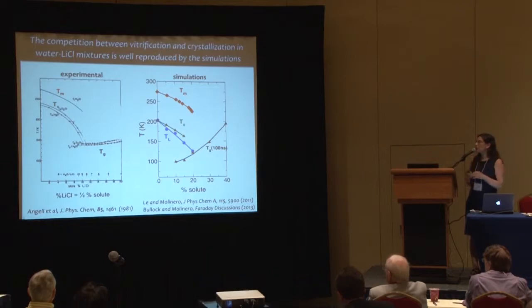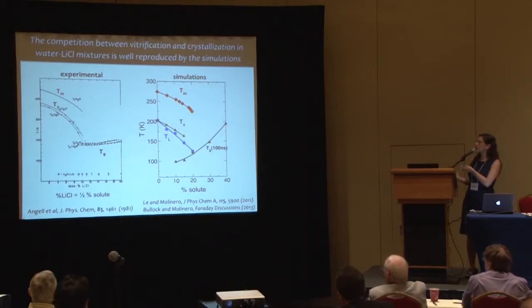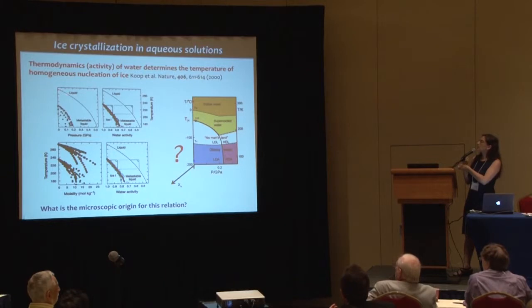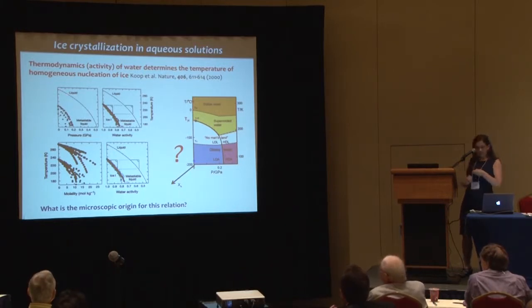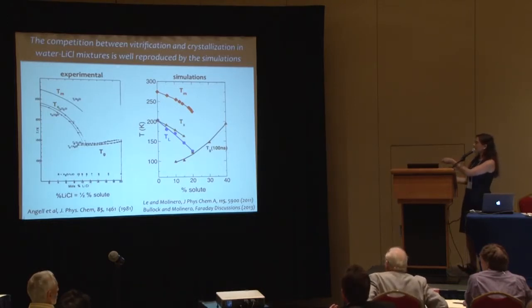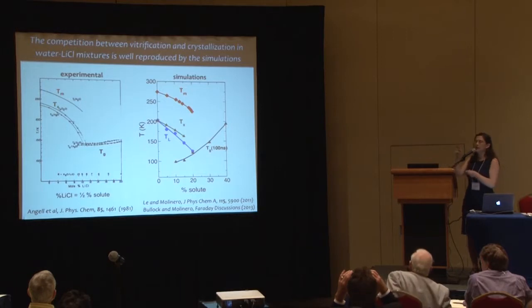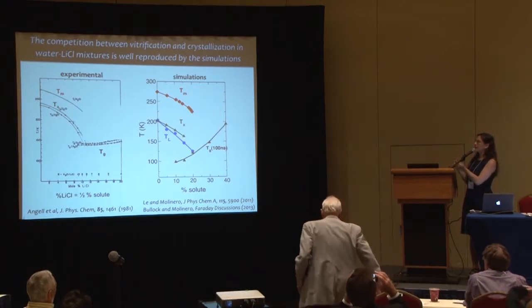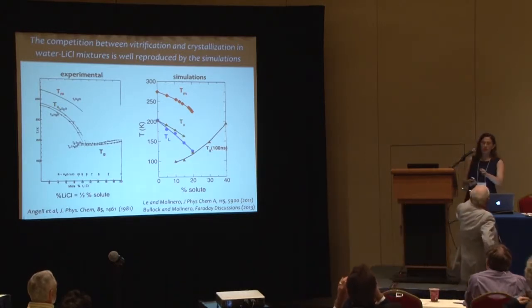I'll now show studies of a simulation system that mimics water with lithium chloride. The experimental phase diagram of lithium chloride shows the melting line TM, a crystallization/freezing line, and a glass line as a function of lithium chloride concentration. In simulations, the melting line is in quantitative agreement with experiments up to moderate concentrations. The crystallization line is displaced down about 25 degrees relative to experiments, as before. There is also a temperature of liquid transformation — the one where four-coordinated domains form.